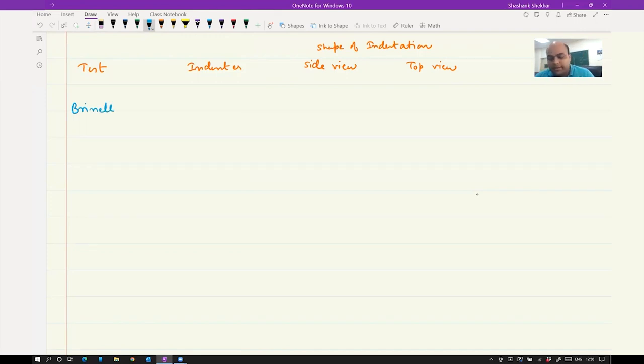And what do we use as indenter in Brinell? Either a steel ball or a tungsten carbide ball, and both are, say, 10 millimeter. So a 10 millimeter steel or tungsten carbide ball. If you see the side view of it, it is going to be spherical. It's a ball, so it is going to be spherical. And if you see the top view, it is going to be a circle. Here we measure D1 and D2, so the average is d. And here your ball diameter is your capital D.